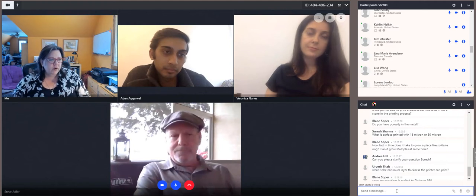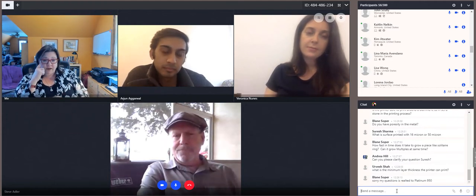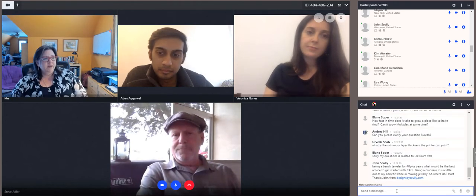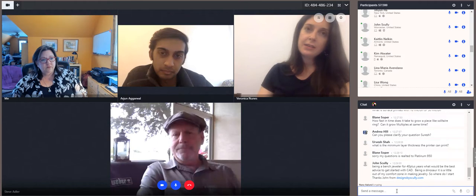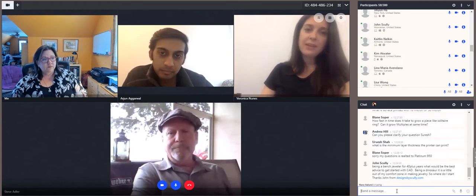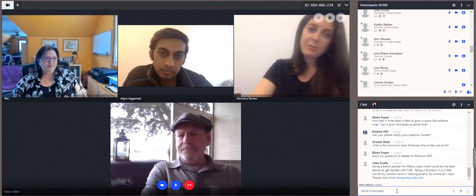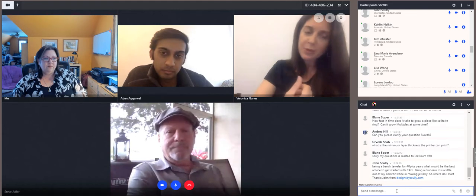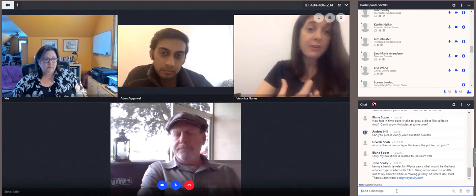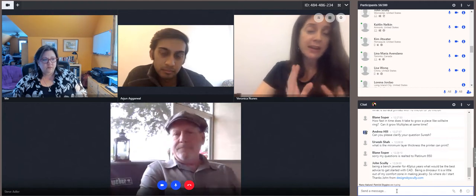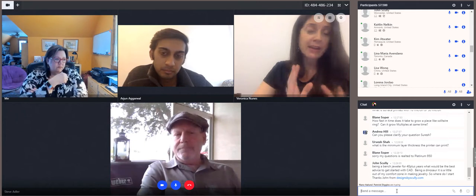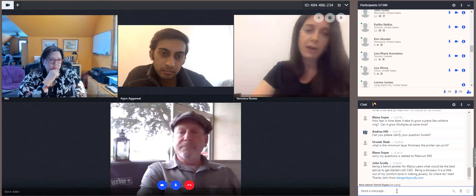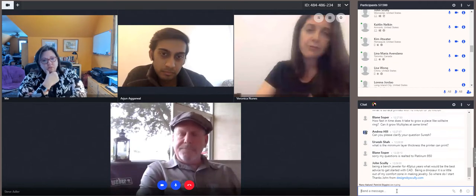So has that been consistent with your experience, Veronica? What are your finishing processes after you grow them, understanding that you're working mostly in titanium, right? Yes, I didn't finish the parts myself. The factory took care of it, but I agree that the 3D printing deposits would have some sort of micro porosities, but it's not visible, at least for me, in the finished parts. It actually looks very good, the finished product. I don't see a visual difference from the casting piece to the printed one. It's not visible for me. Clearly, as you can see, but I'm sure if you put it under a microscope, you probably can see the microporosities there.